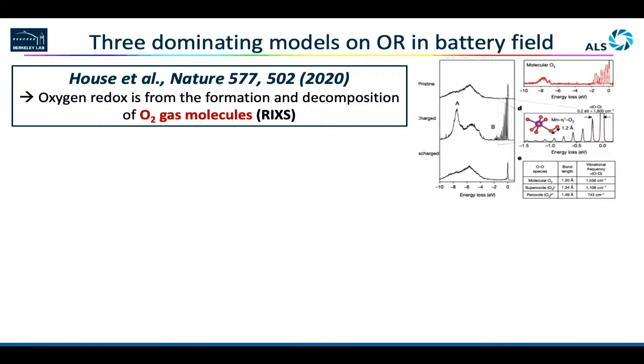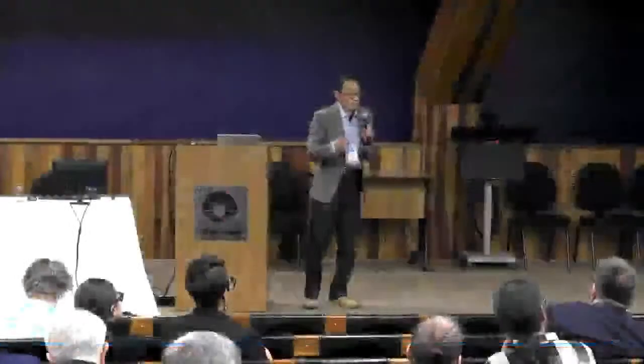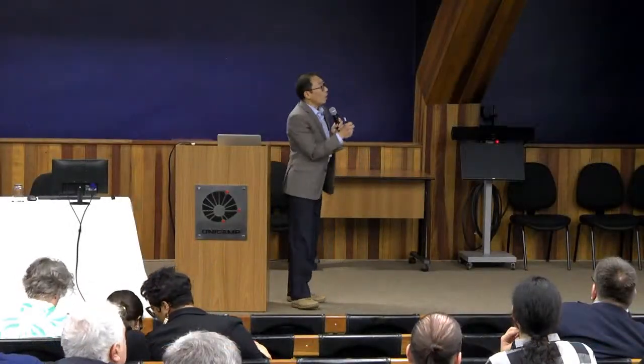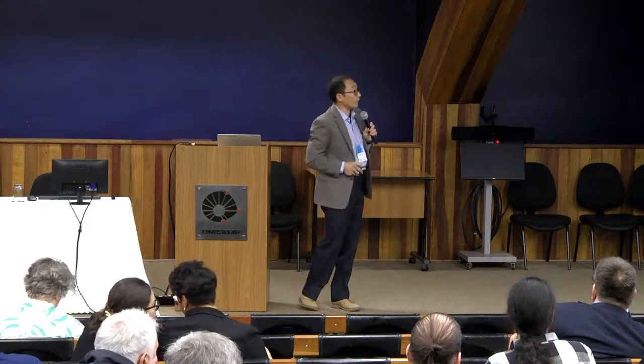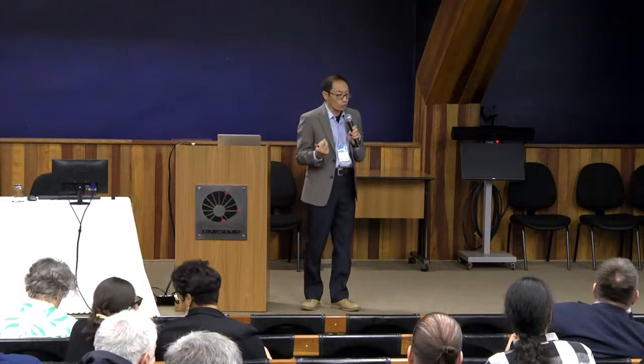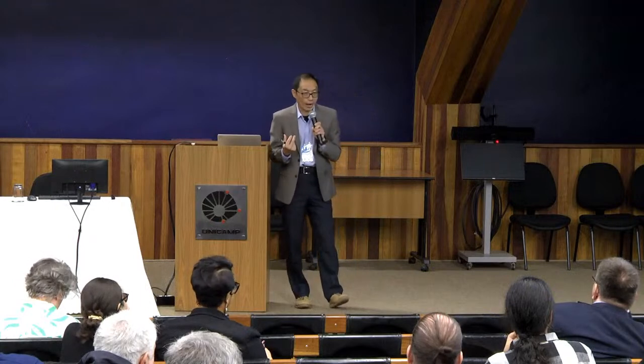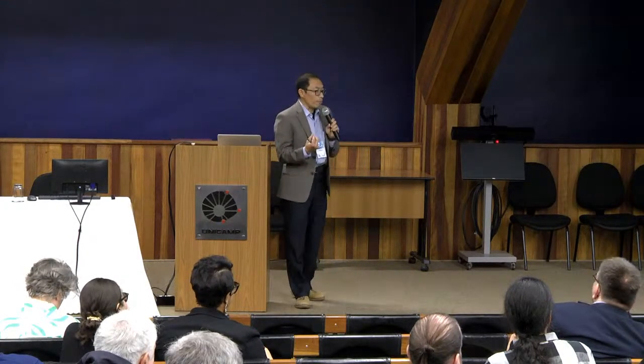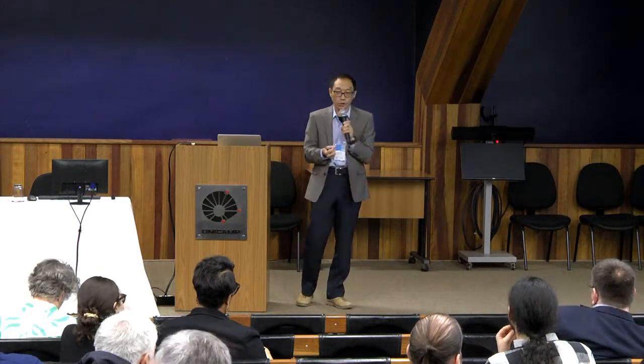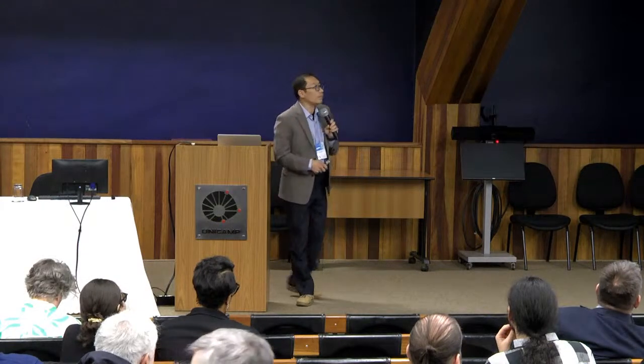Very few groups do not agree with you. Like 99.9999% of papers follow the trend of those three main domains. So one is Professor Bruce in Oxford. They previously had this so-called localized oxygen holes, but recently they have been pushing out a concept to say the oxygen redox itself is by forming and decomposition of oxygen gas molecule that is trapped in the material.